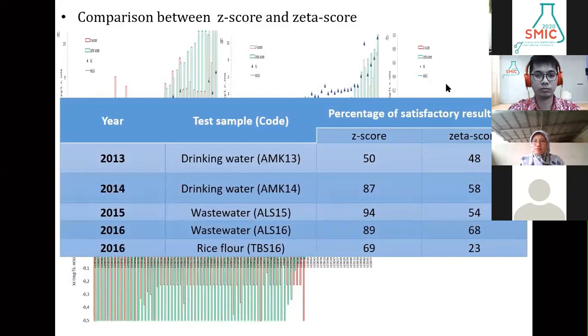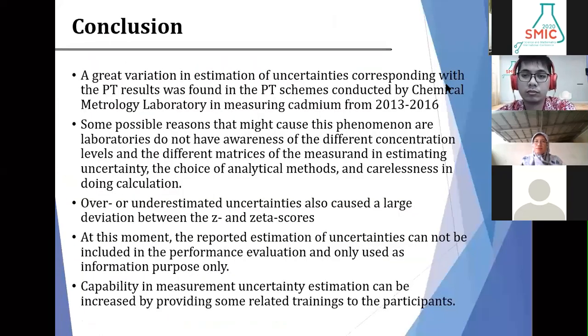Very low or high uncertainties can result in poor performance in the use of the zeta score or in the use of an individual criterion in calculating the Z score. So the conclusion in this study, a great variation in estimation of uncertainties corresponding with the PT results was found in the PT schemes conducted by Chemical Metrology Laboratory in measuring cadmium from 2013 to 2016. Some possible reasons that might cause this phenomenon are the laboratories do not have awareness of the different concentration level and the different matrices of the measurand in estimating uncertainty, the choice of analytical methods, and carelessness in doing calculations.